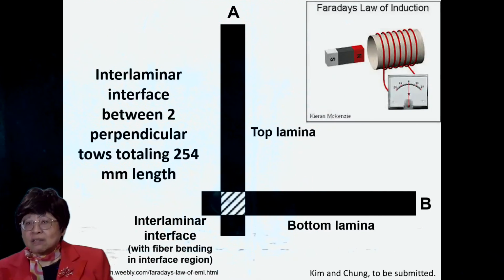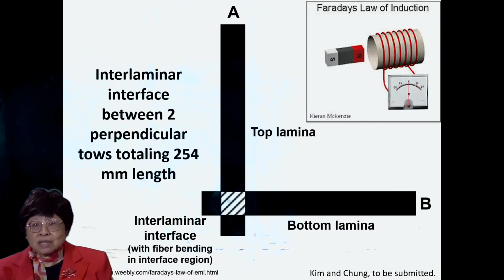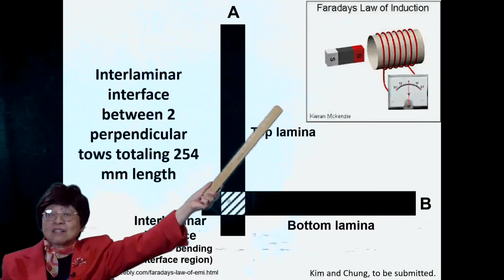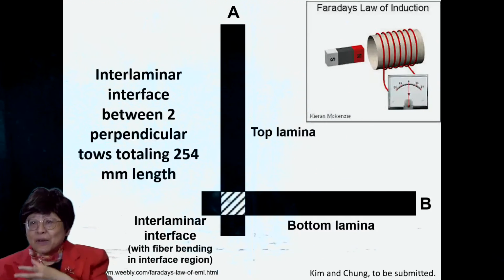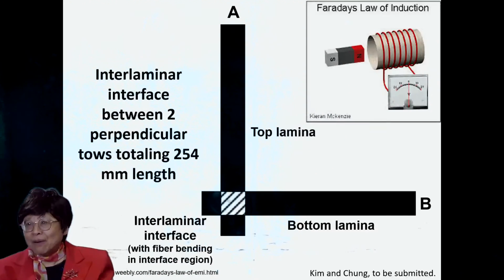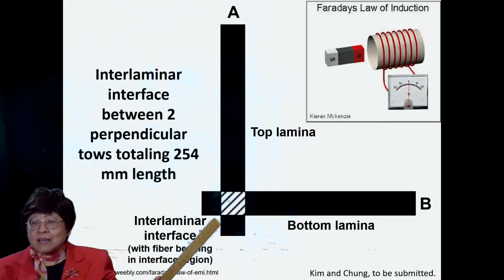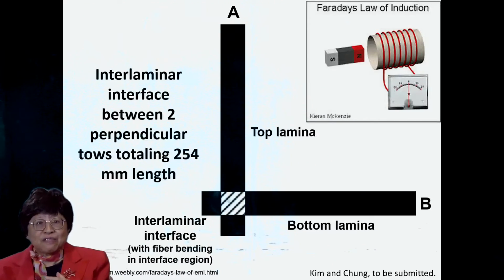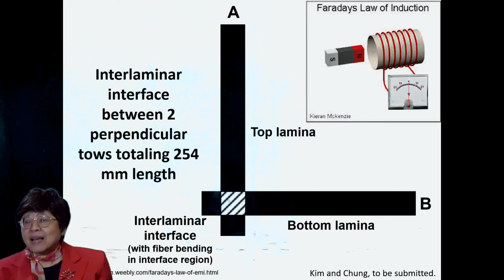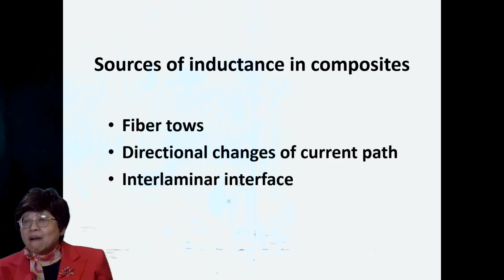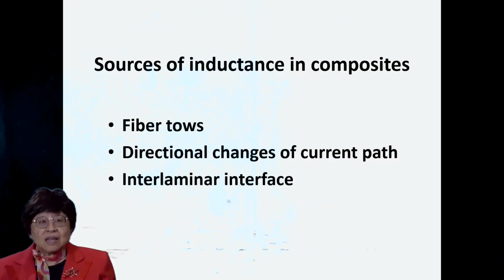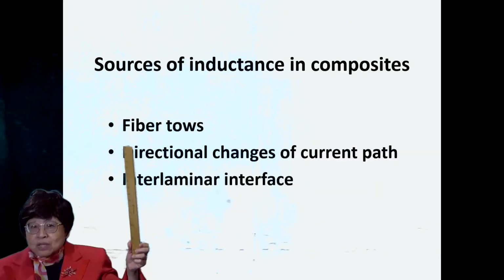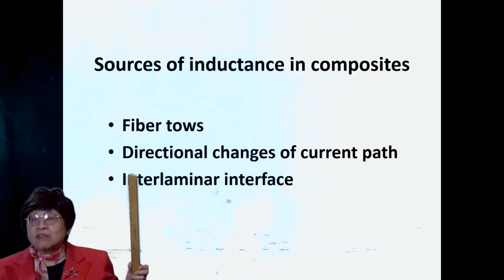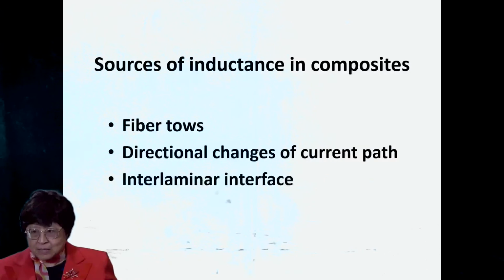This change in direction alone helps to increase the inductance. Just like the classical inductor coil, in that coil, the current direction keeps changing inside this coil, and that's just Faraday's law. In addition, inside the interlaminar interface region, you have fiber bending occurring, and that also helps to increase the inductance. And so there are several sources of inductance in composites: the fiber tows themselves, the directional changes of the current path, and the interlaminar interface.